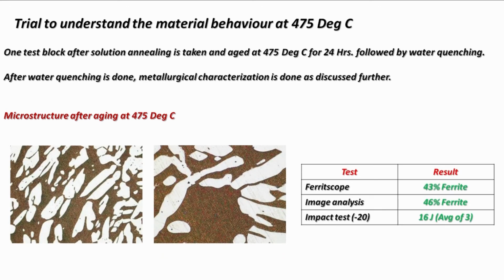But in metallography, we find no difference in the microstructure. There is no differentiation of alpha and alpha prime because it is difficult to segregate the material at microscope level. So further characterization is required, but the ferritoscope, however, shows 43% of ferrite. We have two phases, but it is still showing 43% of ferrite. Why? Because both alpha and alpha prime are magnetic phases. So we cannot segregate through the ferritoscope also.